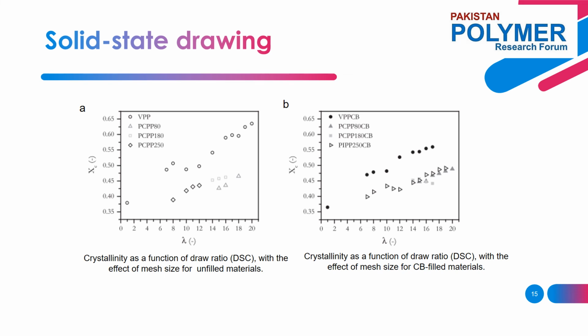Overall, this study presented the potential of the solid state drawing process, which significantly enhances the processing of recycled isotactic polypropylene. It can be concluded that the mild blending method, injection molding, dynamic injection molding and solid state drawing method improve the properties of nanofiller reinforced polymers. The mild blending method improves the properties of polymers which are not affected by water but can cause degradation of hygroscopic polymers. The solid state drawing method enhances the properties of filled polymer by improving the crystallinity and chain orientation of the polymer matrix, but the utilization of a drawing line makes it a complex and expensive operation.